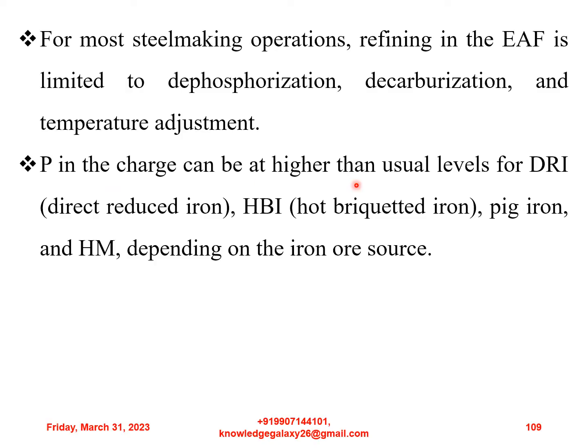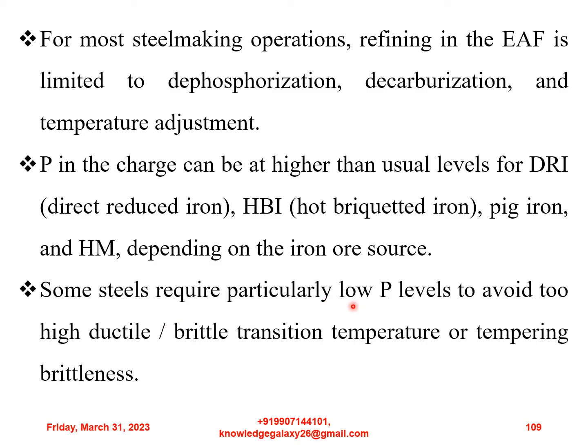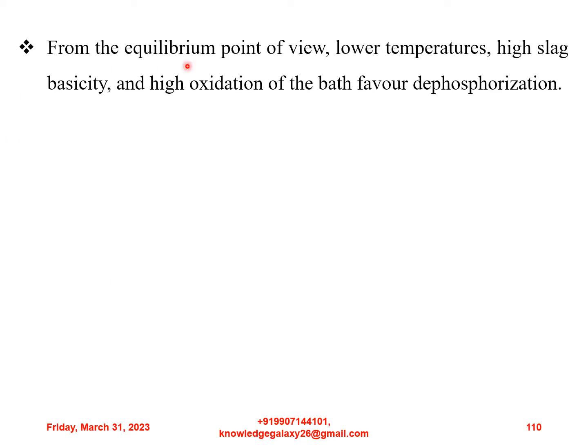Phosphorus in the charge can be at higher than usual levels for DRI and HBI, pig iron, hot metal, depending on the iron ore source. Some steels require particularly low phosphorus levels to avoid too high ductile to brittle transition temperatures or tempering brittleness. From the equilibrium point of view, lower temperatures, high slag basicity and high oxidation of the bath favor dephosphorization. My dear friends, the conditions favoring dephosphorization are lower temperatures, high slag basicity and high oxidation of the bath. Please note it down.